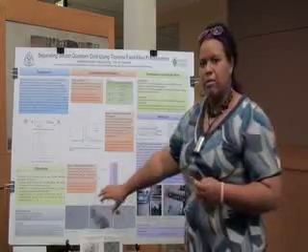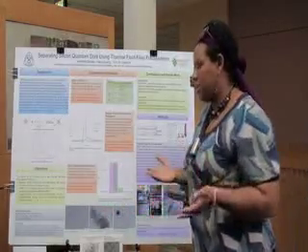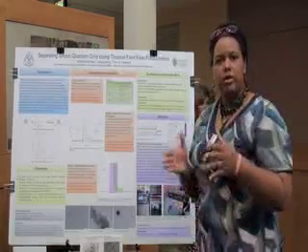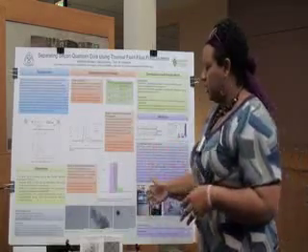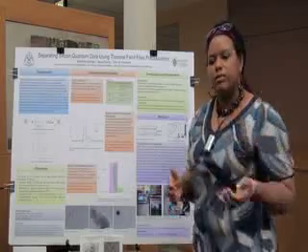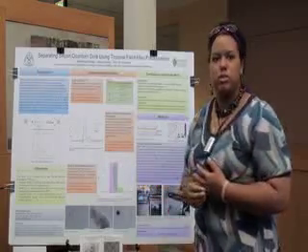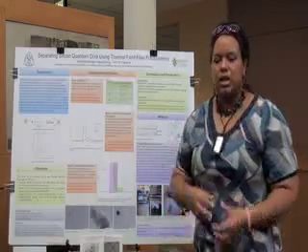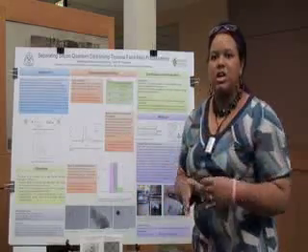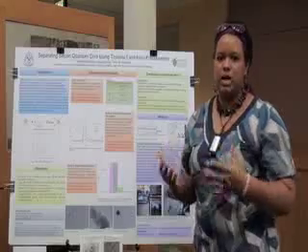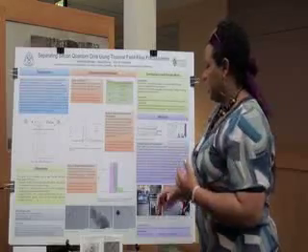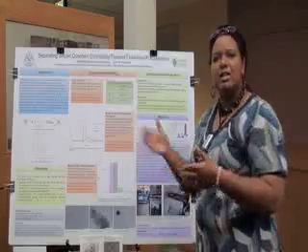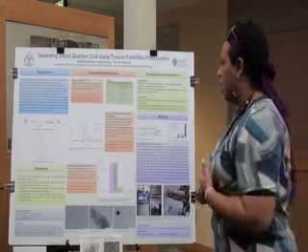The first TEM of fraction 1 indicated that I was getting particle sizes from 2.5 to 4 nanometers, which is pretty good narrow size distribution there. And then the second TEM, I was getting particle sizes from 4 to 6 nanometers, again good size distribution. And this final fraction here, I got a lot of aggregates, and a lot of aggregates that are spherical in shape from 40 to 60 nanometers in diameter. This indicates that I'm losing all the aggregates in one peak, which is very good because we can't really use those, so it's nice to get rid of them all in one peak.